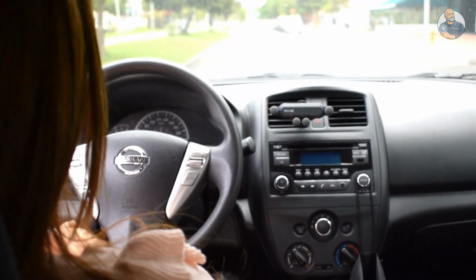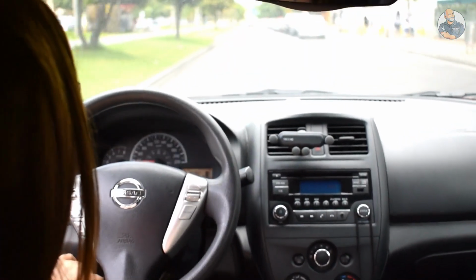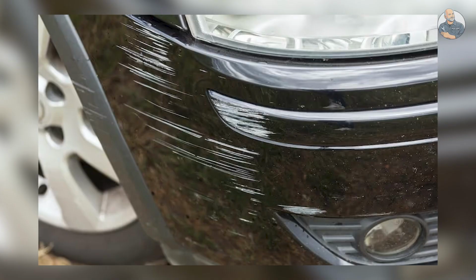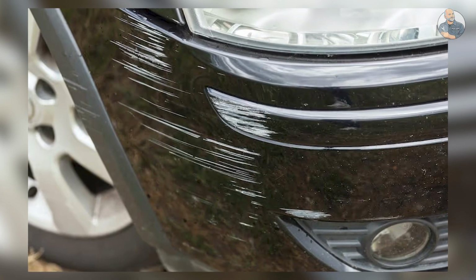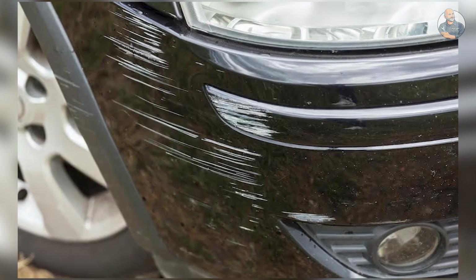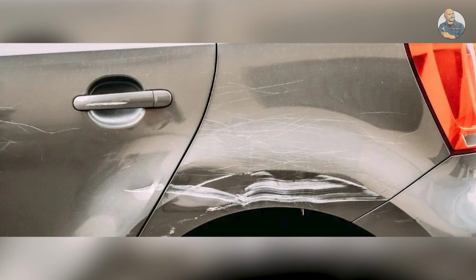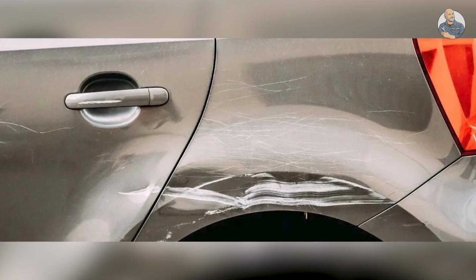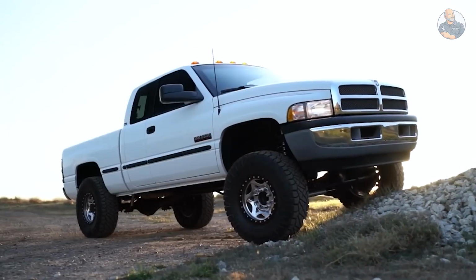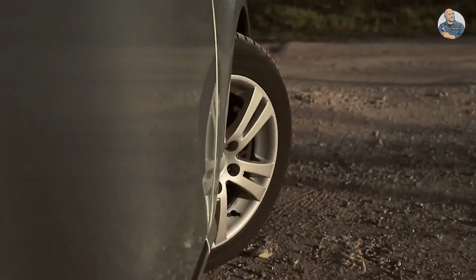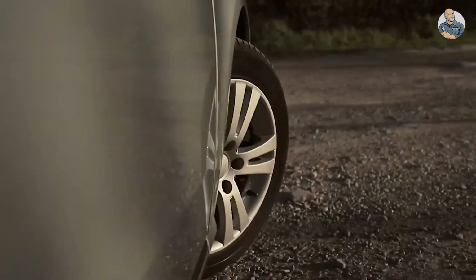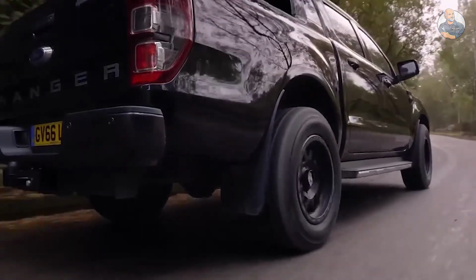But there are two cases you must absolutely avoid. The first, when a scratch is deep enough to reach the metal core or load-bearing structure. The plastic layer is completely torn, exposing metal, leaving no surface for the carbon powder to bond to. Filling the surface in this case is only a temporary fix. It cannot restore the safety or mechanical integrity of the component. The surface may look good, but the underlying structure is compromised.